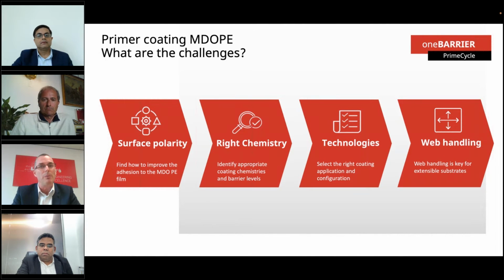The next challenge then was about the primer chemistry. We had to test several different primer chemistries to achieve the best surface chemistry and polarity that gave us a favorable surface for good, what we call nucleation and growth of the subsequent vacuum deposited layer. The next challenge then was application technology. Once we've identified the optimum primer type and the chemistry, we needed to apply these to achieve a good coating laydown with a uniform and closed layer. And finally, for web handling, although the mechanical properties are improved with MDO technology, web handling is still important with regards to tension settings and also the drying profile on the coating line. Next slide, Ben.